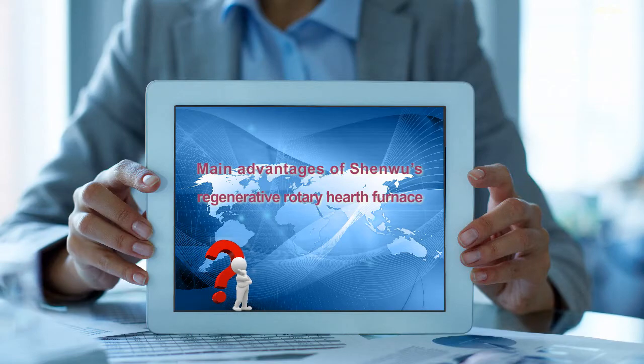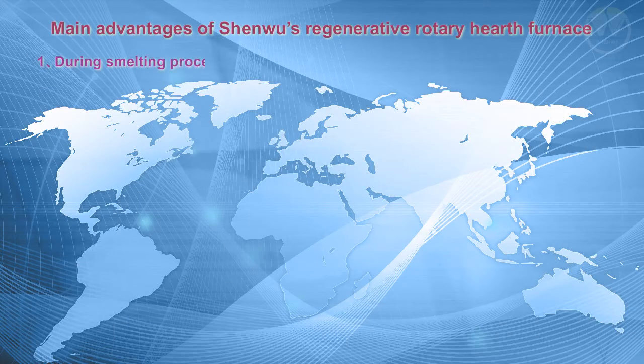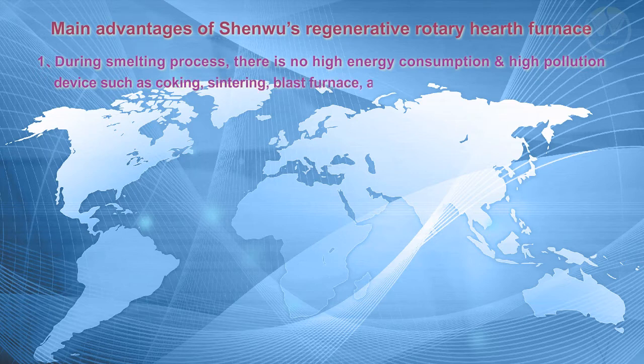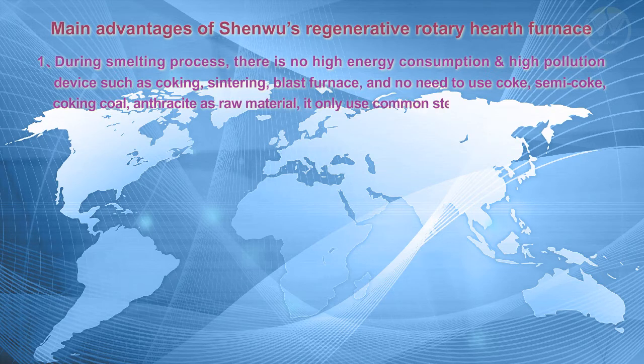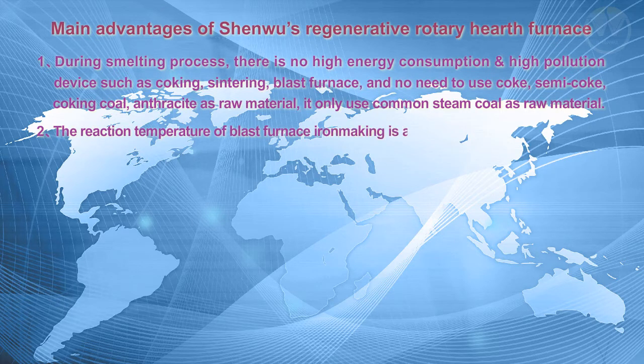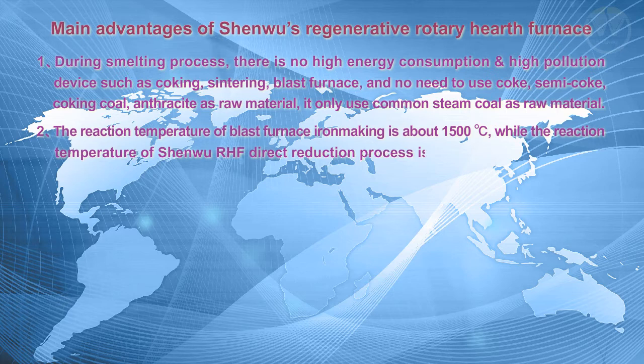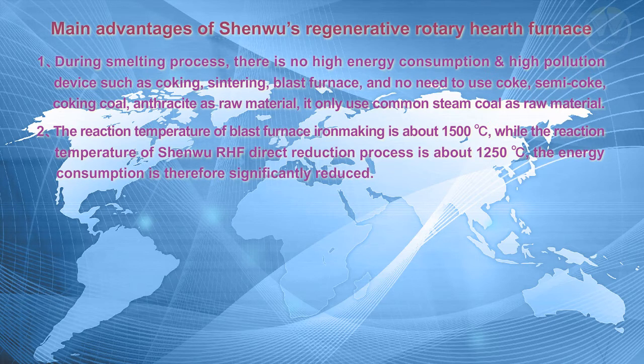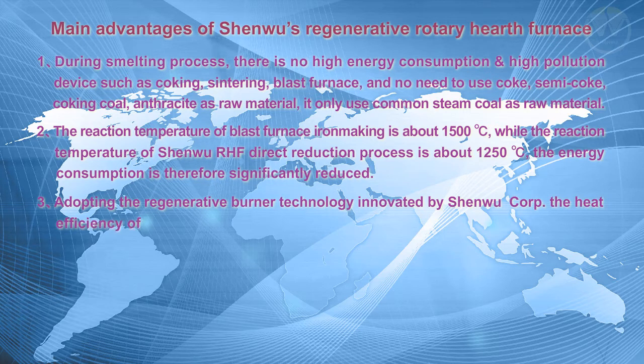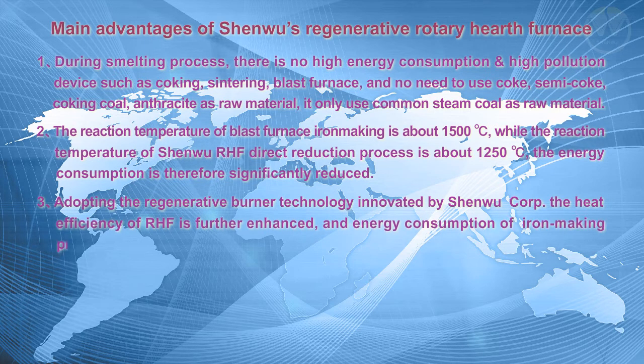Main advantages of Shenwu's regenerative rotary hearth furnace. 1. During the smelting process, there is no high energy consumption and high pollution device such as coking, sintering, blast furnace, and no need to use coke, semi-coke, coking coal, anthracite as raw material. It only uses common steam coal as raw material. 2. The reaction temperature of blast furnace iron making is about 1500 degrees centigrade, while the reaction temperature of Shenwu RHF direct reduction process is about 1250 degrees centigrade. The energy consumption is therefore significantly reduced. 3. Adopting the regenerative burner technology innovated by Shenwu Corp, the heat efficiency of RHF is further enhanced, and energy consumption of the iron-making process is further reduced.